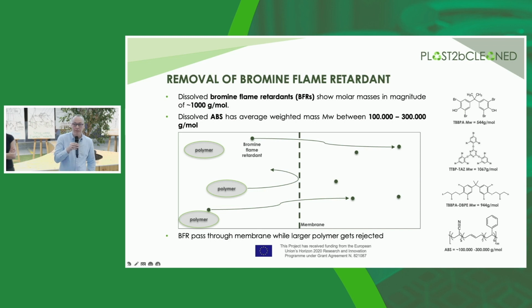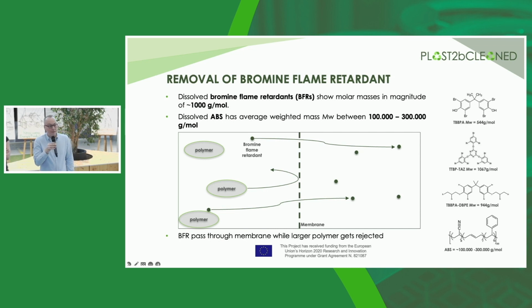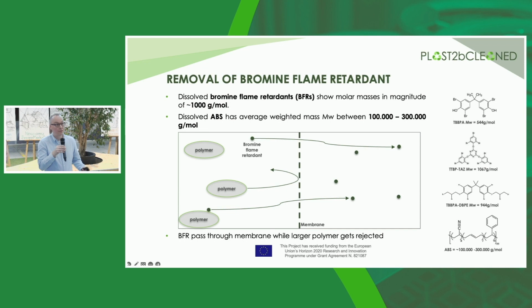Why is that? When we look at the standard bromine flame retardants like TBBPA, we see that we have a molecular weight of between 500 to 1,000 grams per mole, while the ABS usually has a molecular mass of between 100,000 to 300,000 grams per mole. This huge difference in size makes it suitable to use a filtration method. And as you can see in the graph in the center, the polymer is retained before the membrane, while the bromine flame retardant, together with a considerable part of the solvent, goes through the membrane. So this is one method we investigated to separate the bromine flame retardants.